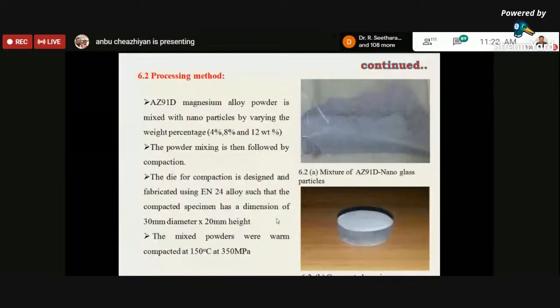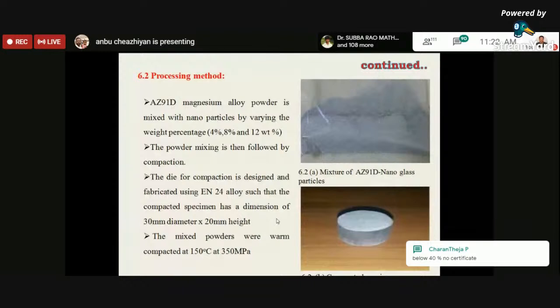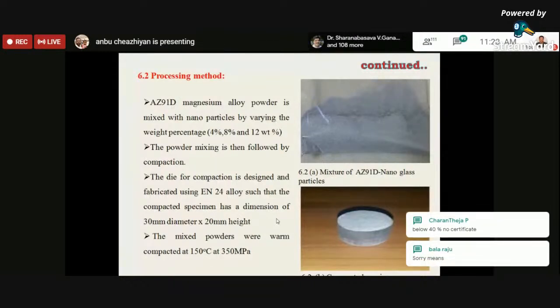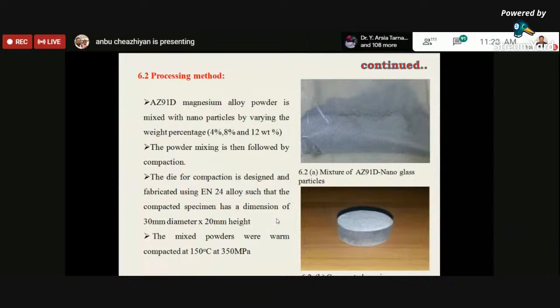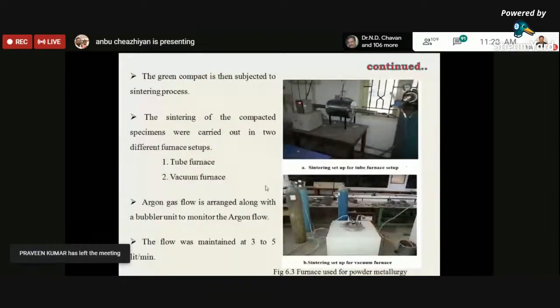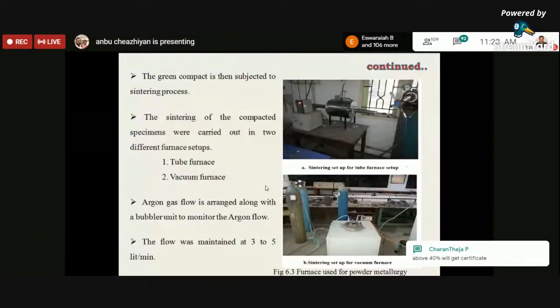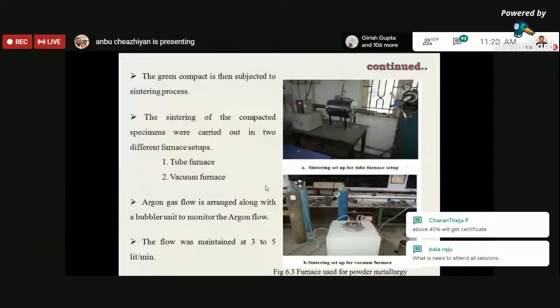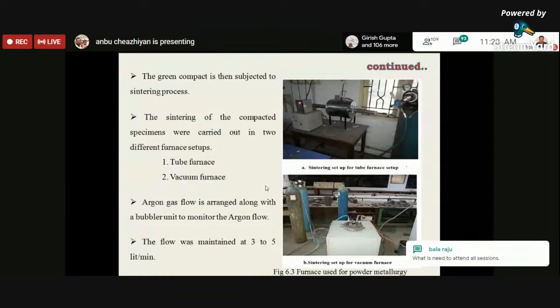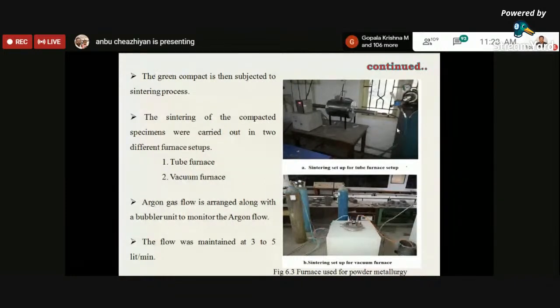Warm compaction was carried out at 150 degrees centigrade at 350 megapascal. We have not increased the compaction pressure, since it is a borosilicate, it should not break or tend to deform due to the warm compaction. So we have given 350 megapascals. Here we used two furnaces for sintering of the nanoglass particle reinforced magnesium composites. One is a tube furnace and the other a vacuum furnace. These are available at NIST.